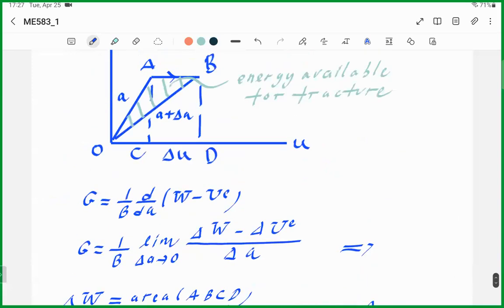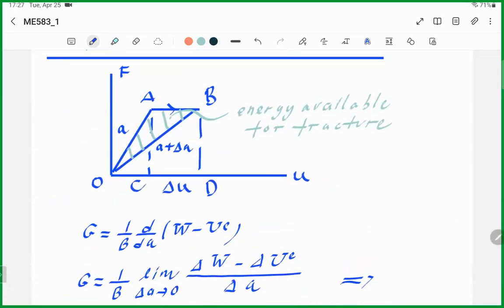Now as you see in this diagram, crack length is changing from A to A plus delta A. And once the amount of energy available for crack propagation is this area, and if it can counter the resistance of the material against crack propagation, the crack will extend and crack propagation is going to occur. Therefore, this is the fracture criteria, and this is the basis of stress intensity factor criterion as well.